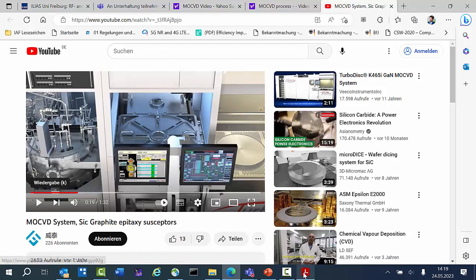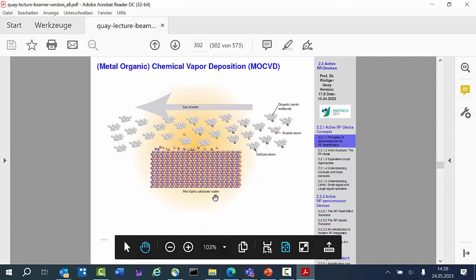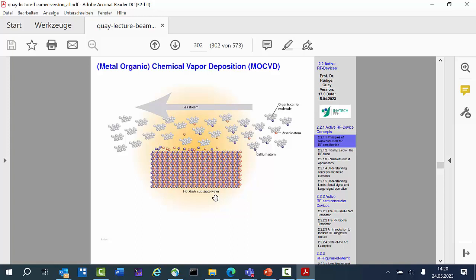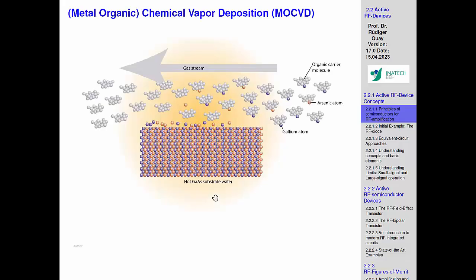And the trick is then, why is this procedure so nice? Because you can also grow at a substantial growth rate, because you make an atomic growth, but you also want to create a significant layer of this, because if you're thinking you're depositing atom by atom, you're turning crazy. Yeah, and for example, one application where we need this, all the white LEDs are produced in this way. So all the lights we have on this planet, they are grown in this fashion. So you need a certain growth rate just to make it happen, because if it takes days,